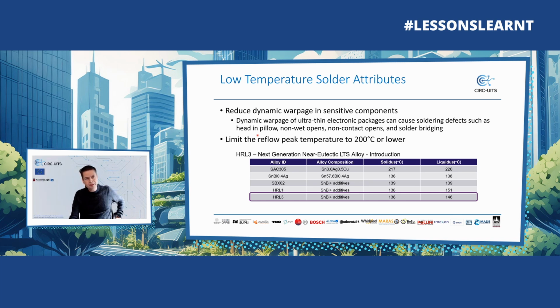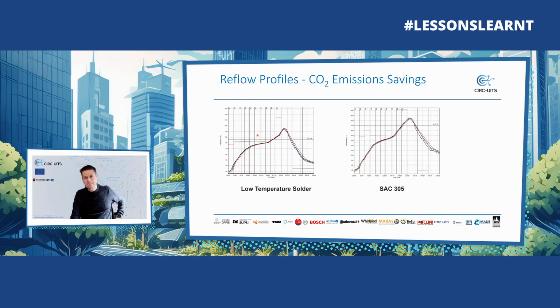We as MacDermid Alpha did extensive testing also of the reduction in CO2 emissions. So we ran tests. We created a very extensive calculation model in Excel, where we compared low temp solder alloys to SAC 305, and we used these reflow profiles, solder profiles if you like. This one, low temp solder, has a peak at 190, whereas the SAC 305 has a peak of 245 degrees C.